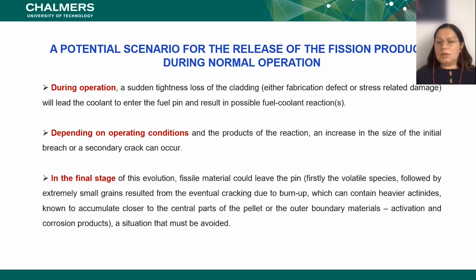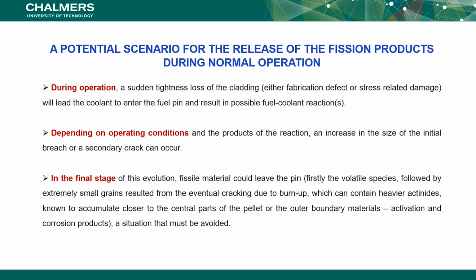And this can increase the size of the initial breach to a secondary crack. So you can really have a crack in the material. And then in the final stage of the evolution, the fissile material can leave the pin. And what is leaving first and how depends a little bit on the type of the damage. But of course, if it's a small damage, then you have these kinds of steps.